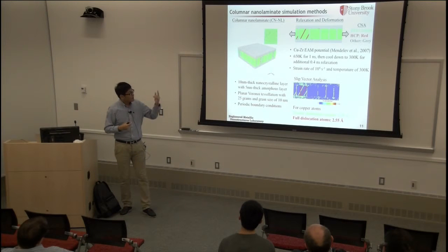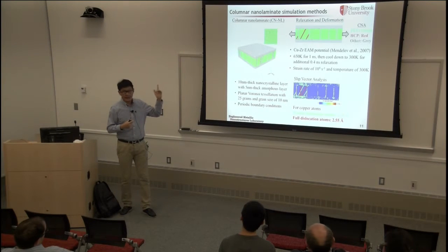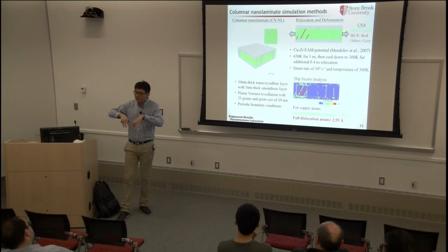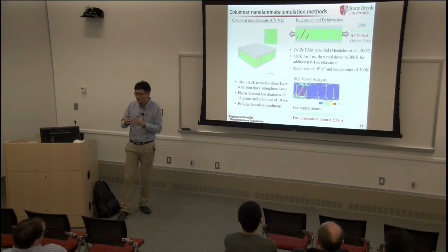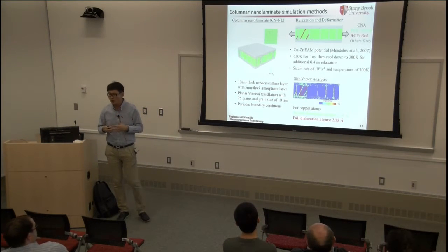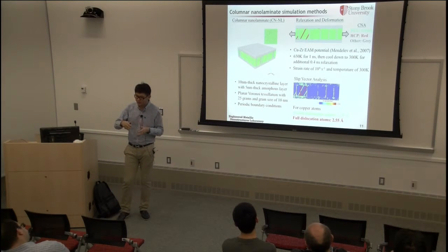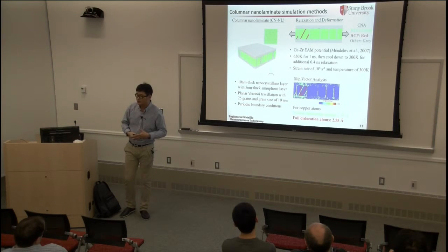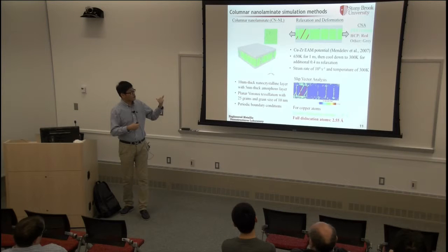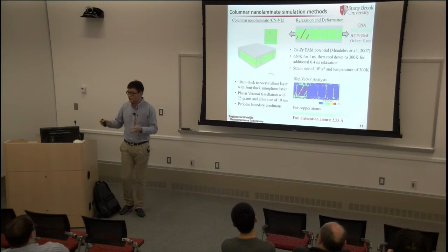Also, because this is a textured material, it's going to have a really small misorientation angle, which leads to a really small angle dislocation grain boundary. Then we use another Monte Carlo process to make most of the grain boundaries high angle grain boundaries. So that's how I made this initial structure, and all the other structures are produced in the same way.